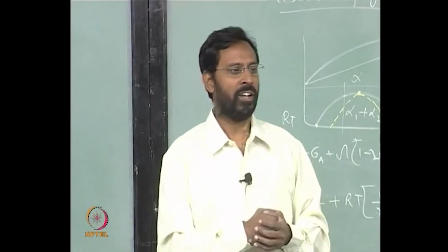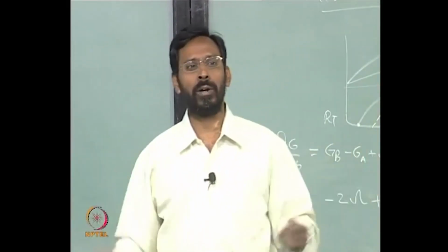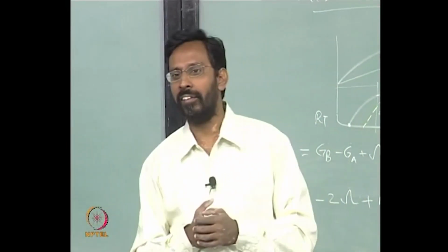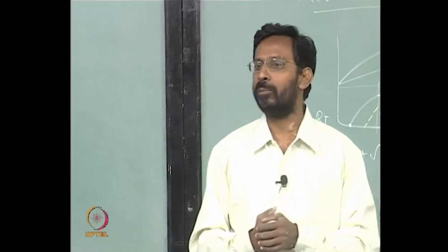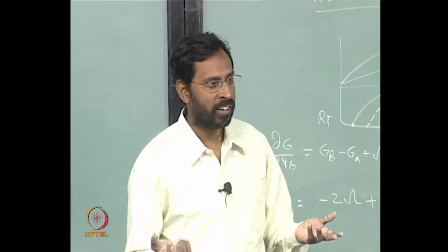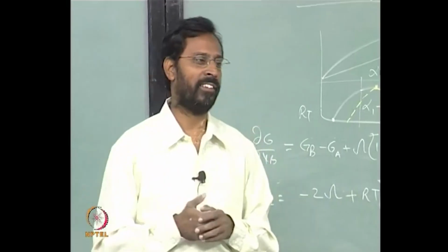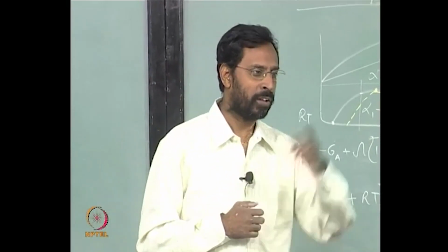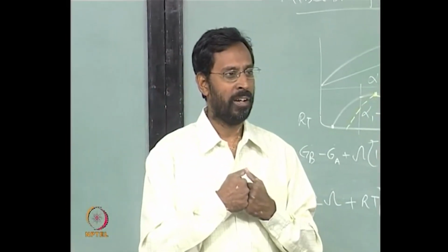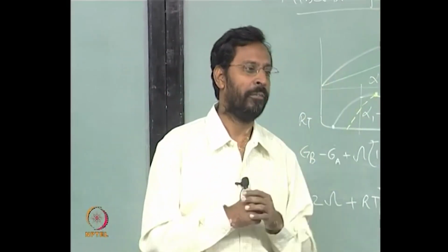So you put those elements, that is why not every 2 elements, just because for example I take some multi component system, 5 elements, it does not mean that every 5 elements if I choose I will get a glass. For example, we are working on what are called high entropy alloys. In high entropy alloys we do not get a glass, we still have 6 elements, you can even put 8 elements, it does not mean that it will give a glass. So just because you have more elements, that is where you have to look at whether they have a strong attraction first of all, because liquid gets stabilized only when the delta H mixing is negative.